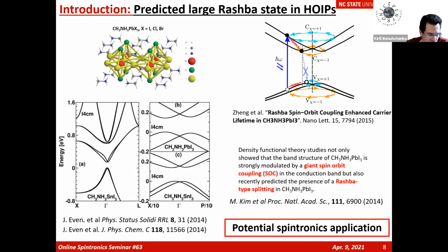So here in this picture, is this also for the surface? No, that's for the bulk. But for the bulk, doesn't symmetry forbid Rashba splitting? So that's what Professor Evans calculated. That's for MAPbI3. At low temperature, it's a trigonal structure. It does have symmetry breaking. For our calculations, MAPbBr3 at room temperature is cubic. So that's the difference. In the bulk, we don't have a symmetry breaking.